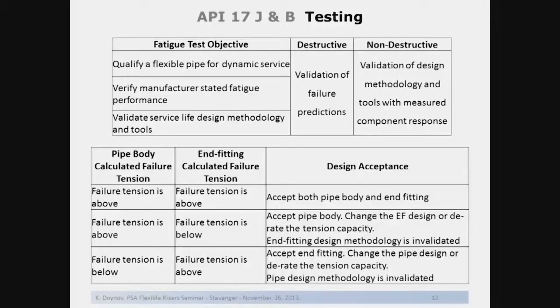The bottom table presents examples of different design acceptance criteria for, let's say, tensile failure of flexibles, where we have a failure in the pipe body versus failure in the end fitting, and different scenarios. When the predictions of the failure tension in the pipe, for example, are above the ones that we measure, but the predictions of the failure tension of the end fitting are below what we measure, then the acceptance criteria is accept the pipe body, change the end fitting design, or derate the tension capacity, and rethink your end fitting design methodology.